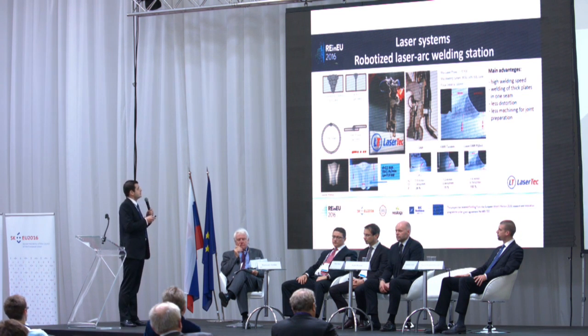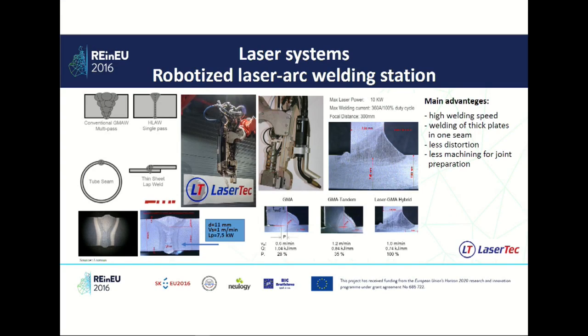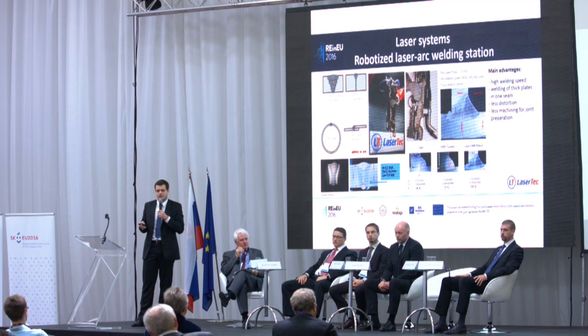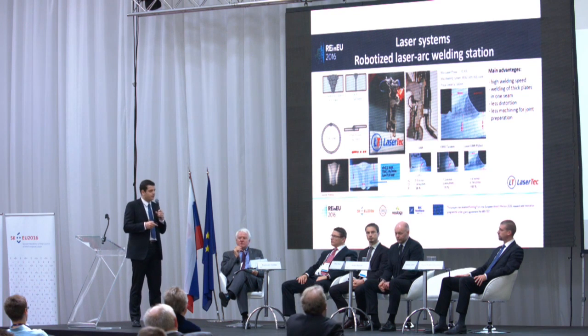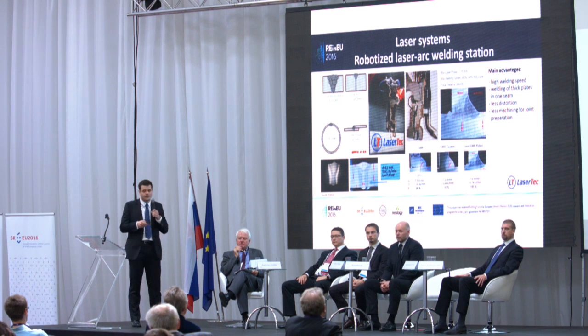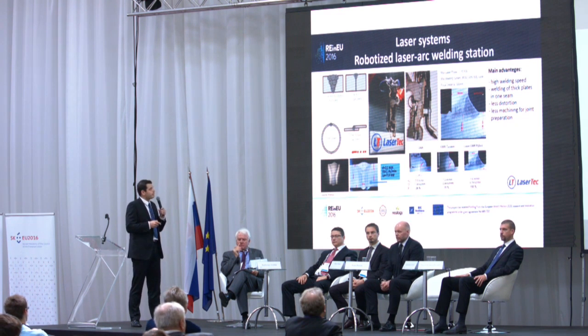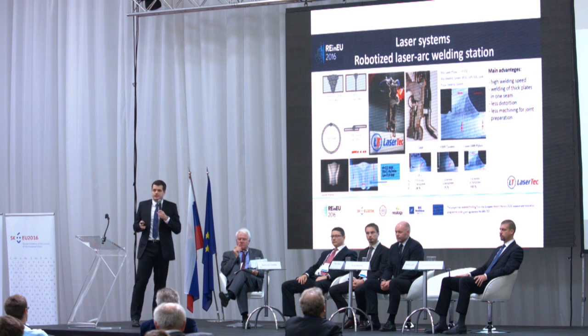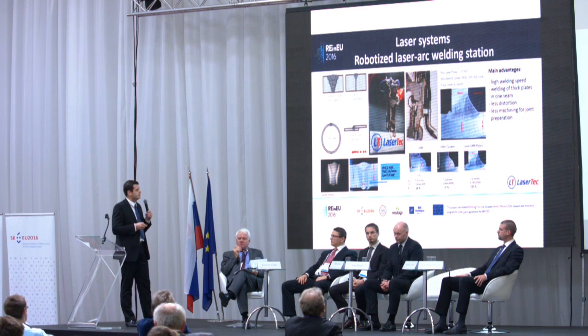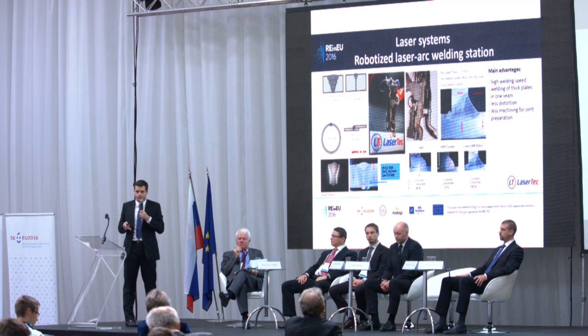As you can see here, in the standard arc welding process, you have to mill the joint, then you have to fill the joint with several seams. With hybrid welding technology, it's possible to do it in just one seam, so it's a much faster process with higher welding speed, and you do not have to weld in several seams. This is mainly used for thick plates, because you can use the laser to have very deep penetration welding. Less distortion. Laser technology in general gives a much smaller heat input to the element.